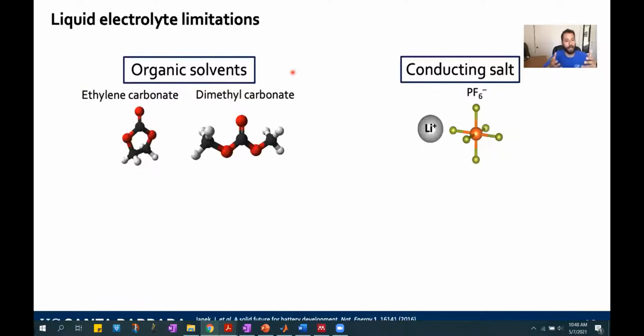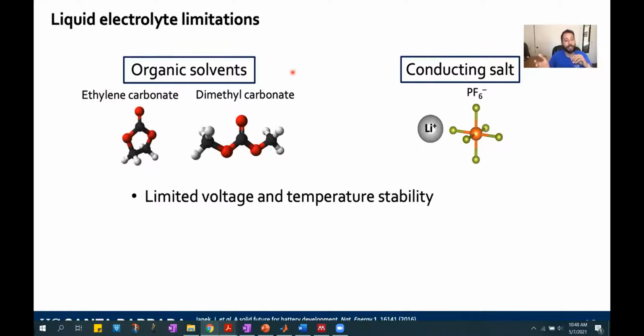So this liquid electrolyte that I mentioned previously, unfortunately has some pretty severe limitations. So they're made up of these organic solvents like ethylene carbonate and dimethyl carbonate, as well as that conducting salt like lithium PF6. One of these limitations is that the voltage range of stability of the organic solvents, as well as their temperature stability, is pretty limited. And that's because they will tend to break down at higher voltages, or they'll sort of volatilize at higher temperatures.